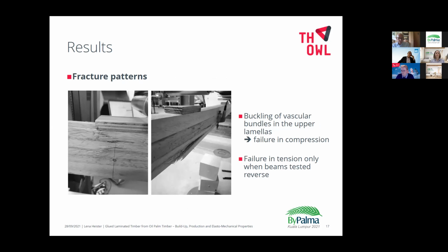After the compression failure, the beam continued to fail on the outermost lamella, loaded as tension, and below the compressive failure. To avoid buckling of the vascular bundles, some beams were tested under upside down loading of the lamellas. This means that the lamellas with the higher density are on top. The result shows different fracture patterns. A total of 5 beams of strength class C10 were tested under reverse loading. 3 beams failed in tension, 1 in shear, and 1 in compression as in the previous ones.